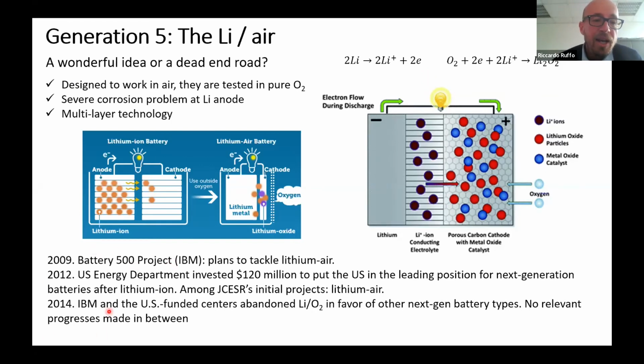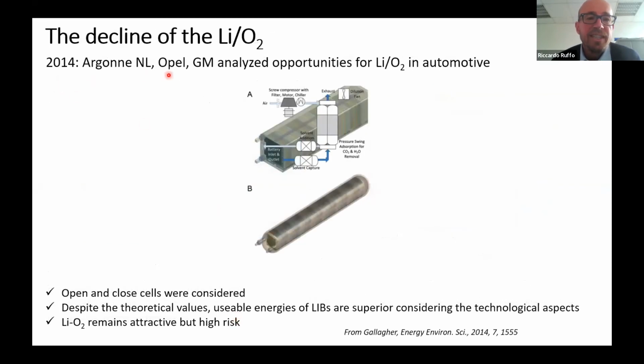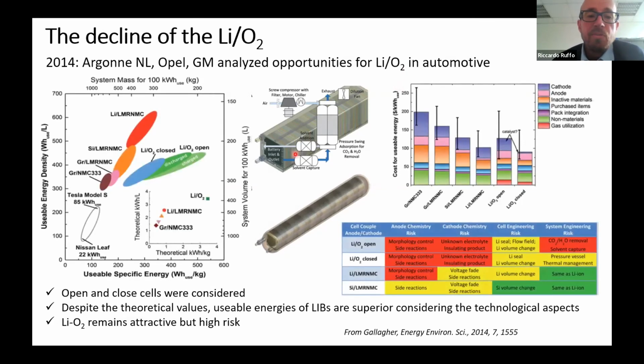Around 2010, there were a lot of investments in the development of this lithium-air. However, in 2014, there was a lot of analysis about the system. First of all, you cannot use air here, but you have to use pure oxygen. Otherwise, your device is not working properly. And then several calculations about possible devices equipped with oxygen cylinders or open to air with a catalyzer and so on provided figures of merit which were not really so satisfactory. So most of the big players now have abandoned this kind of research.